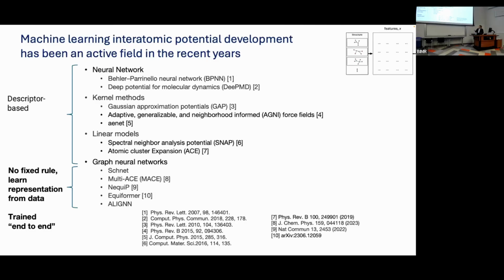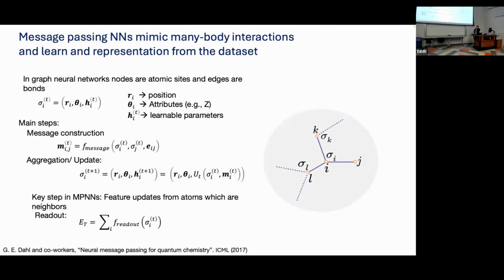There's been much work on these representations. One key innovation was what's called message passing. So how does that work? Here we have, instead of a three-dimensional structure and considering bond distances, we still have this cutoff, but now we represent it as a graph. So we have a series of sites that are treated as nodes, and the edges are just the distances. So any atom within the cutoff radius is related to the central node based on an edge. The edges themselves are represented here.